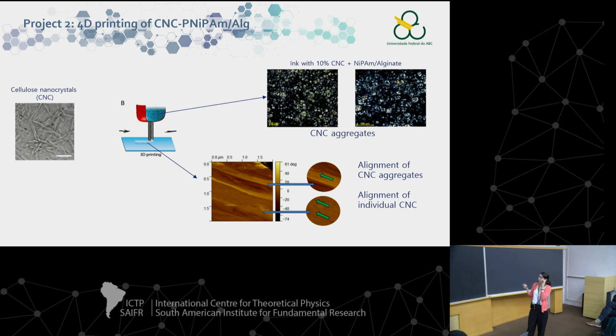We had a lot of difficulty dispersing the CNC in our ink. Here it's an optical image, and we see aggregates of CNC. We tried a lot, and we didn't succeed in making them disappear. So we said, let's try to print it and see what happens. We printed it, and then we checked our filament by atomic force microscopy. On the screen it's not so good, but we see some regions where we have alignment of CNC aggregates, and some regions with individual CNC that are aligned with the shear stress.